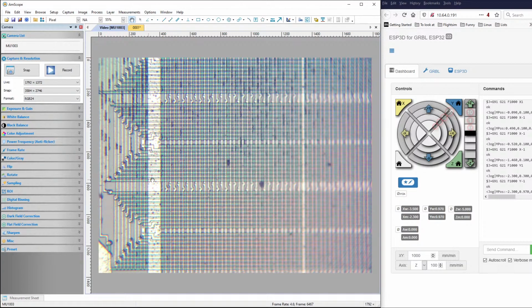It's very sharp on this side of the image, whereas if I start going over to the right, it gets blurry, and it's the same. Top is sharp, bottom is blurry. This is due to the tip and tilt not being correct. The focus depth of the microscope is so short, and the thickness of the die and the layers of the die is so thin that if you don't have it absolutely level, you get these issues. And much of my setup time is actually spent on making sure that I get this leveled correctly.